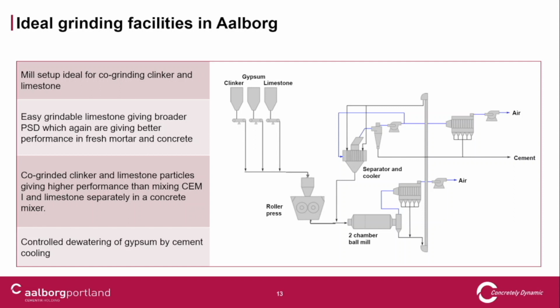Without going into details, our milling facility is not just a ball mill. It consists of a roller press where everything goes through and gets pre-crushed. Then it goes into a two-chamber ball mill, but then the materials go through a separator. We can control how much of the largest particles are separated and returned to the ball mill, and decide the fraction of how big the returned particles should be.